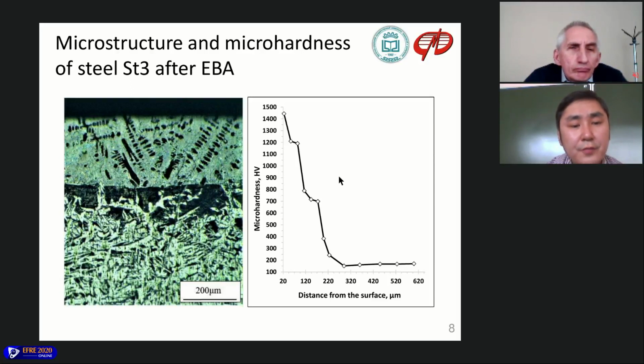Also, in the base metal a ferrite-pearlite microstructure is visible, and also a pearlite-rich zone in the transition zone just below the coating. Also, microhardness distribution showed that the maximum microhardness is 1400-1500 HV on the top of the layer, and then values slowly decrease to a value of around 200 HV in the base metal.